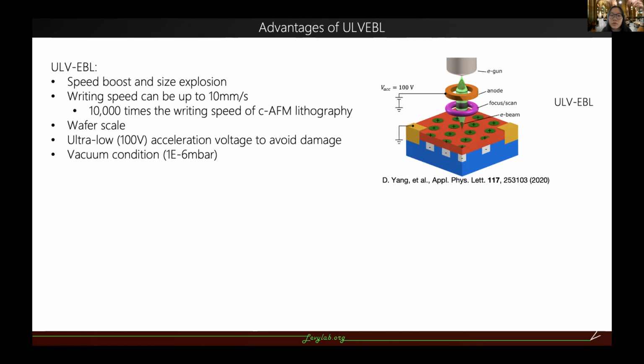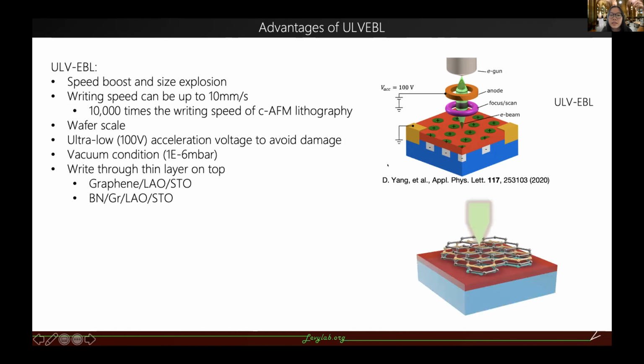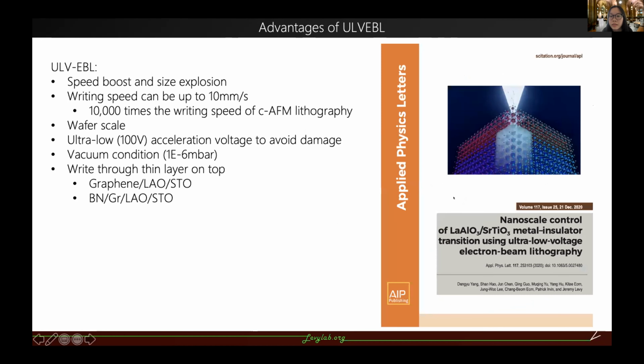Here we use an ultra-low acceleration voltage, at around 100 volts, to avoid damage to the oxide structures. During the exposure, it's in a vacuum condition, so that makes the device preserve itself longer in the vacuum. And more interestingly, we found we can write right through a thin layer on top of LAO-STO, such as graphene or boron nitride-graphene stacks. We are still able to write through it and create connecting structures at the LAO-STO interface. We published our preliminary data in APL, and it was selected as the cover and featured article of that issue. So please take a look if you're interested.